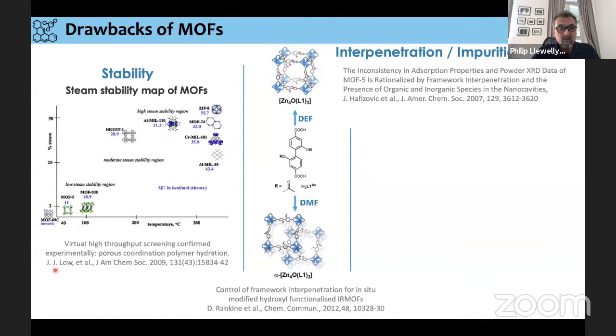So this work back in 2009 showed that they could carry out steam testing, so taking the materials, synthesizing them, treating them under steam for a certain amount of time at different temperatures. And they've compared this to the percentage of steam, and this has been compared with molecular modeling to get an idea of the stability of the materials. So we can see down here that maybe some MOFs are not so stable, but there are other MOFs, and we'll maybe talk about ZIF-8 later, which are quite stable.